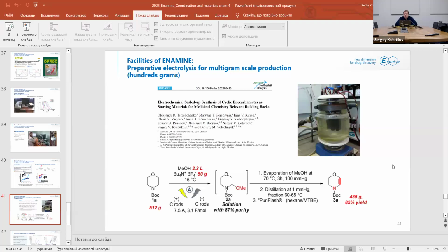Also, we developed a procedure for preparative electrolysis, and we could find conditions for production of Boc-protected cyclic carbamates in multi-gram, in hundreds of gram scale. And I would say I think it's a success, because these compounds, especially this compound, were not commercially available, and those which were available were very expensive. After our work, we can make these compounds much cheaper and much more efficiently compared to the previous methods.